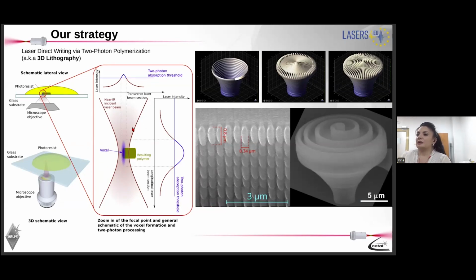The physical principle behind the 3D printer I showed you before is two-photon polymerization using laser direct writing. Briefly, we put a drop of photoresist on a glass substrate, or it can be other type of substrate, not only glass. And on this photoresist, we focus very tightly a femtosecond laser beam. Here, at the focus point of the laser, polymerization takes place. This is the only place that the polymerization occurs, within the whole volume of the photoresist. And this small volume, which is polymerized, is called voxel. Voxel is actually known as the elementary unit of any kind of 3D structures printed in this way.